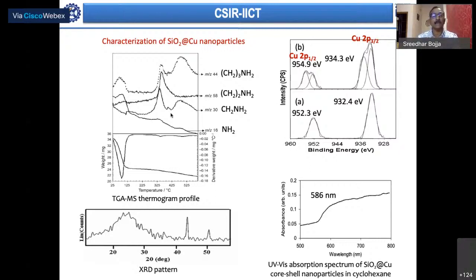In this case, you see an initial peak, a weight loss, followed by a gradual weight loss up to about 600 degrees centigrade. This initial weight loss is due to the solvents present—in this case water, so it is dehydration. If it's an organic solvent, it is desolvation. Depending on the medium in which these particles are dispersed, you have different solvents, so the initial weight loss is due to the solvent or dispersing medium, causing dehydration or desolvation, followed by gradual weight loss.